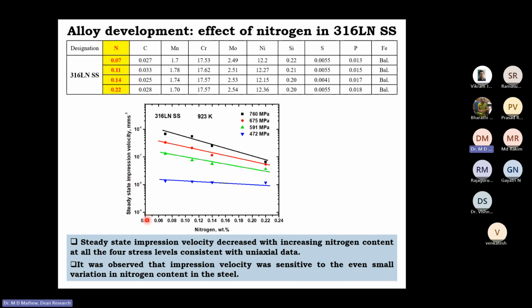So this is the steady state impression velocity as a function of the nitrogen content. This shows the variation of the impression velocity as you increase the nitrogen content from 0.06 to 0.22 at an impression load of 472 megapascal. And the other straight lines represent the data obtained by carrying out impression tests at other different loads with equivalent stress. So what you see here is as the nitrogen content increases, the steady state impression velocity decreases. So the material becomes creep stronger. And of course, as you increase the stress, the steady state impression velocity increases.